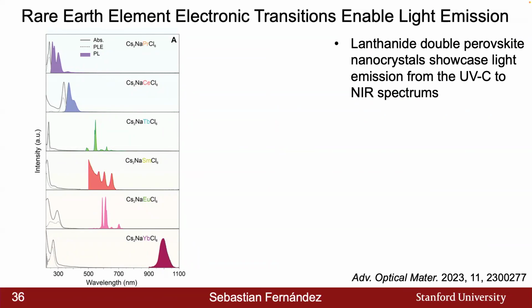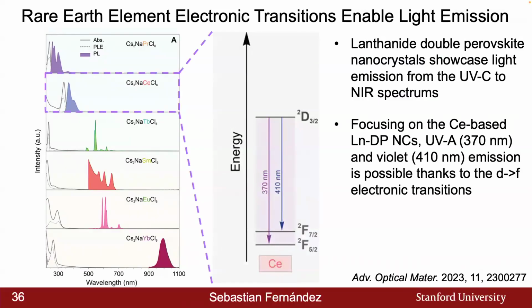And so recently there have been reports of lanthanide double perovskite nanocrystals, which can showcase light emission from the deep UVC, based on the praseodymium-based materials, all the way to the near infrared spectrum, based on the ytterbium-based materials. Now here I'll briefly highlight the cerium-based perovskite, which, thanks to these d to f electronic transitions within the material, has this doublet emission. You can see two peaks here in the photoluminescence that are thanks to the transitions here, so a peak at 370 and 410 nanometers.